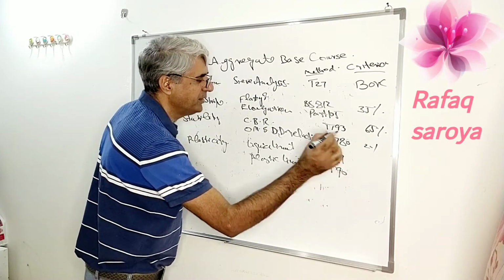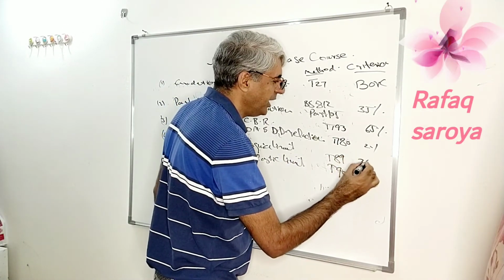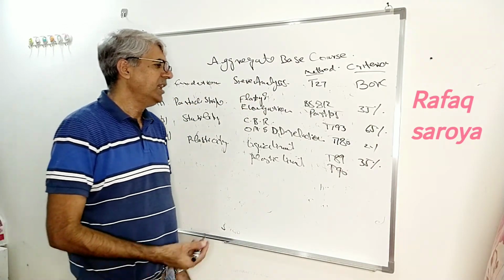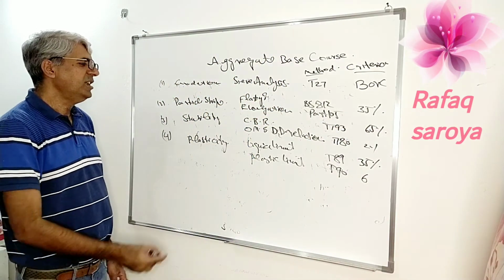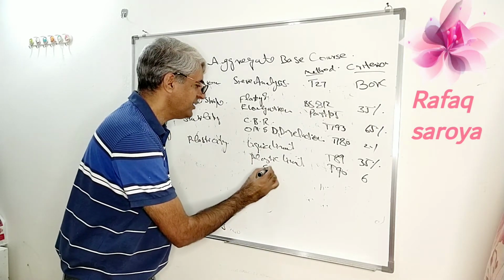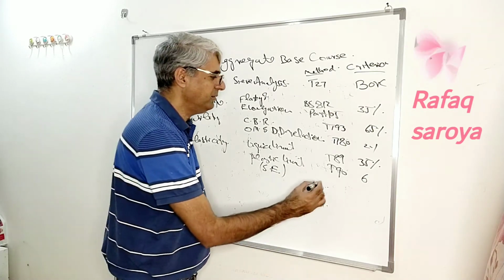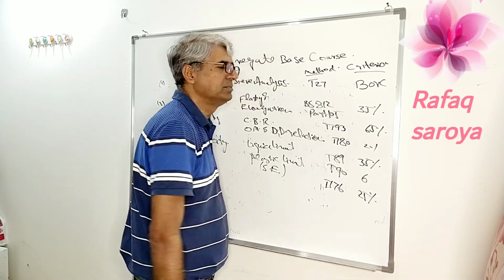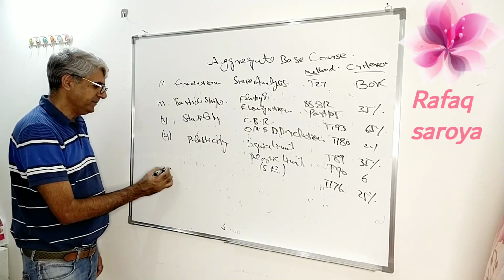T89 says the liquid limit should not be more than 35, and the plastic limit, or the plasticity index, should not be more than 6. Sometimes the sand equivalent is also mentioned. The sand equivalent is determined by the T176 method and its value is 25%. Below this, the material is not acceptable because it is going to give us contamination.